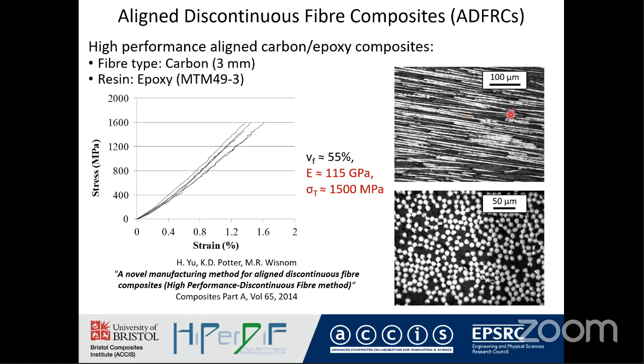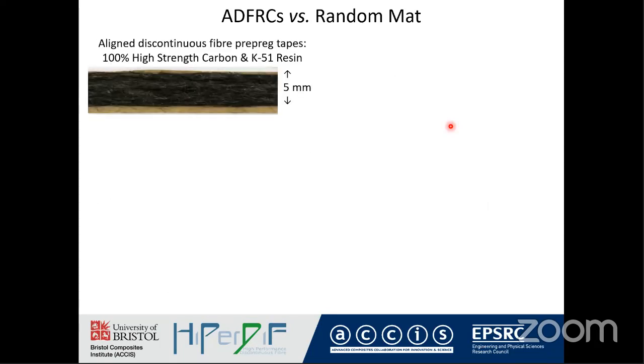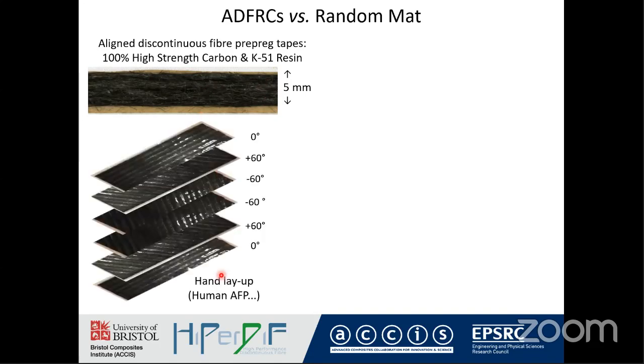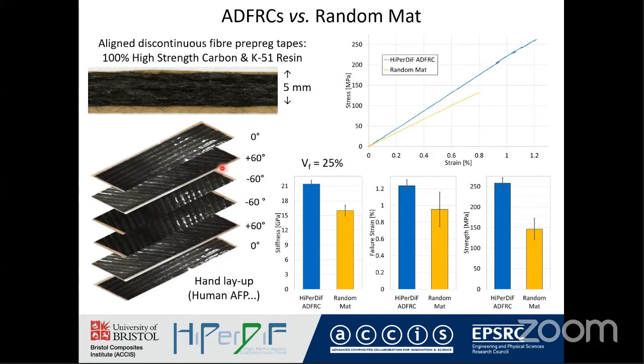Now you can see from the micrographs on the right hand side here the level of alignment, which is high. Now why do we perform this? If I compare the data of our tape, in this case containing purely high-strength carbon fibers with an epoxy matrix, this is very much sort of human AFP, if you like. It's a hand layup, but you can see it's quite laborious in this sense, producing it from these very narrow tapes. But in this case, as you can see, a quasi-isotropic layup, which produces, in this case, a fiber volume fraction a little lower at 25%, but the data here are the random mat, and the data for the ADFRC from HiPerDiF is shown in blue.